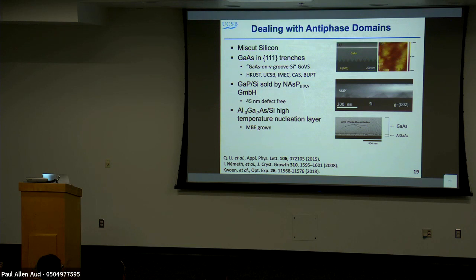But how do you solve that then? One approach is to grow on these 111 surfaces. So if you look here, you can see these 111 surfaces. And the period here is typically about 200 nanometer period. And because of that, you get defects, but they all grow along those 111 planes, and they terminate at the top of those little points. They don't propagate up into this layer. So up here, you get actually low dislocation, zero antiphase domains. So that's an approach, and we've made lots of lasers that way.